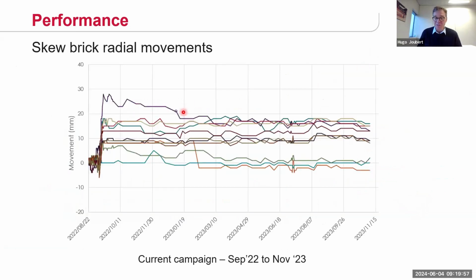Another very positive consequence of this design is the skew brick radial movements. So following the initial heat up of the furnace, you can see these skew bricks completely stabilized. Sibanye is actually really good at monitoring the skew brick positions on a regular basis around the circumference of the furnace and looking at the radial movement outwards. And you can see it completely stabilized inside the furnace. This is all the way to November, end of November last year. And this is compared to previous campaigns where the radial movement continued to take place throughout the campaign.